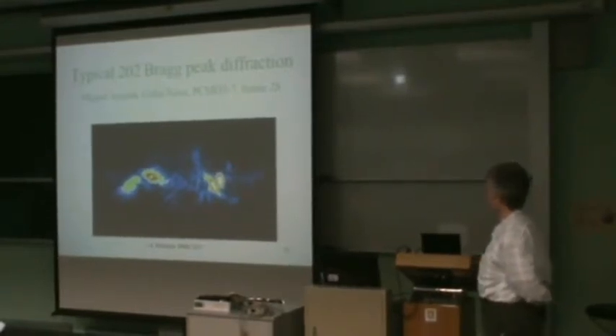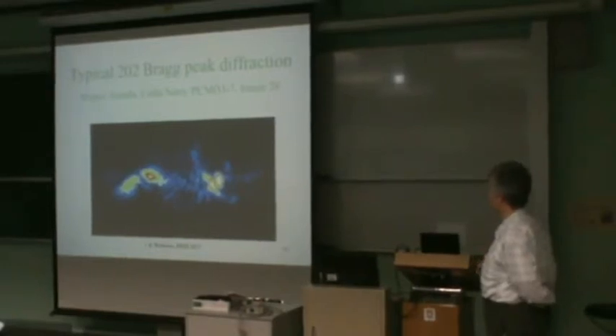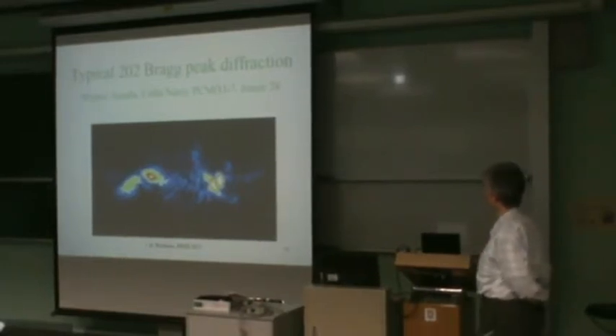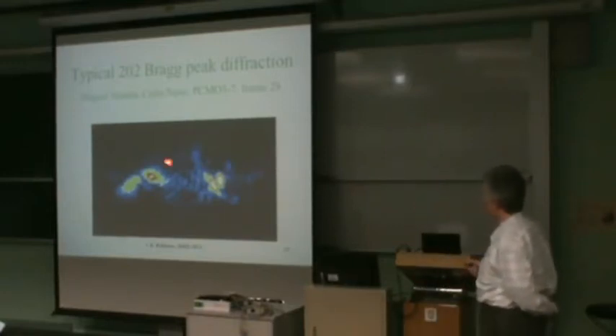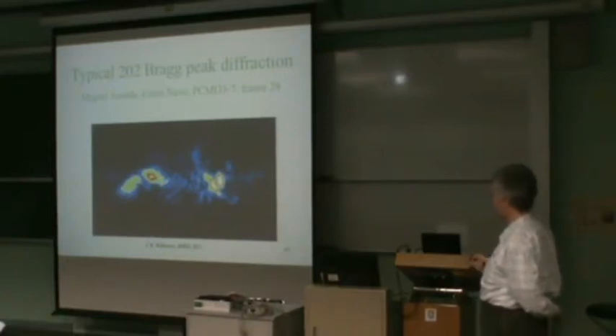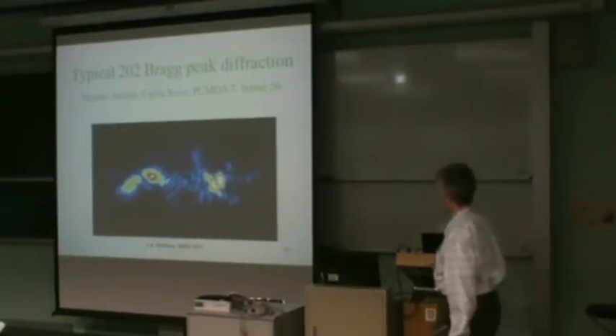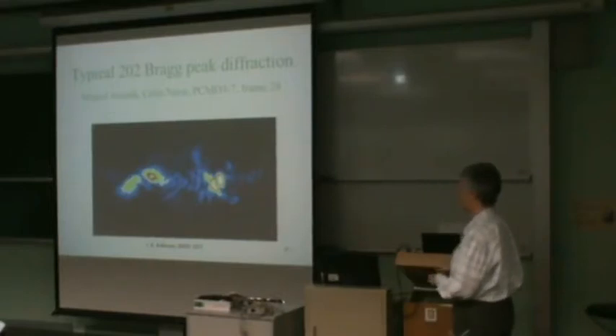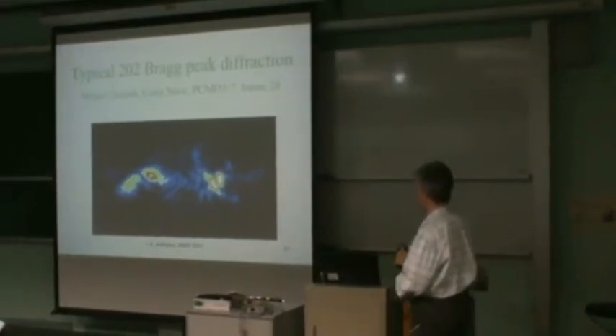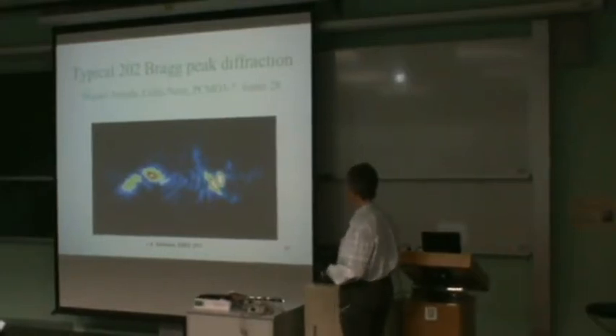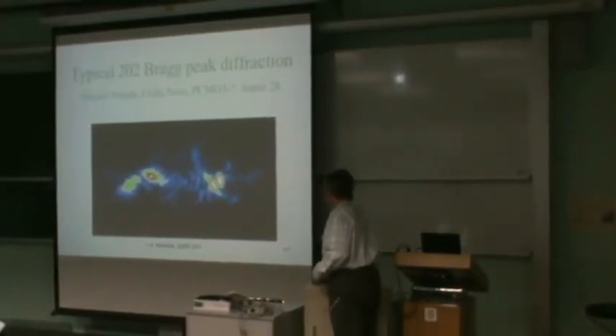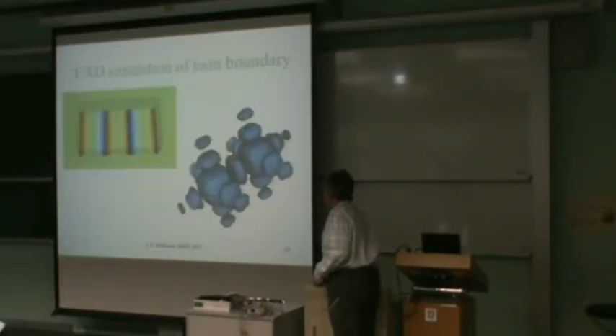This is a PCMO crystal, not a semiconductor material, but this is praseodymium, calcium, and manganese oxide, excuse me. It's got one of these tetragonal distortions with twinning, and you can see, we've seen several examples of split Bragg peaks. We haven't been able to image the domains that correspond to this, because this corresponds to much more than 2 pi phase shifts, and so we've not been able to invert the diffraction patterns, but we've at least been able to see a couple of examples of them.